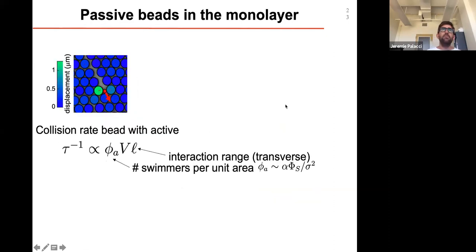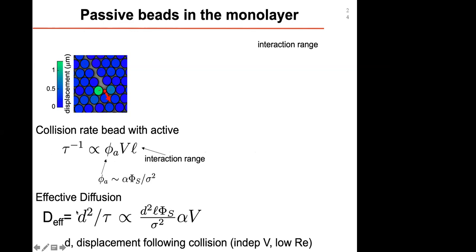Can we understand that? Let's try to see what actually happens. Here, the figure on the top left is an actual picture of the experiment where the color of the big spheres is a reflection of their displacements. You can see that all the blue particles basically didn't move. The red particle is the active one, and we can see that it's moving by unzipping the crystal, and most of the displacement is transverse. Now we can ask what the collision rate of the passive bead with an active particle is. The collision rate is going to be proportional to the number of swimmers times the cross section, which is going to be the speed of the swimmers times the interaction range, the transverse interaction range.